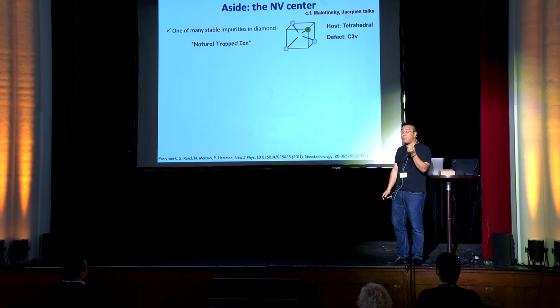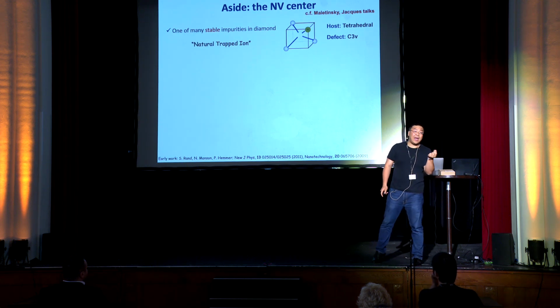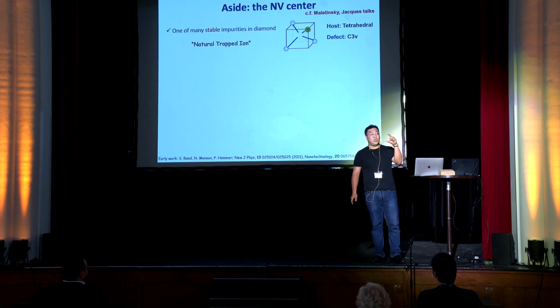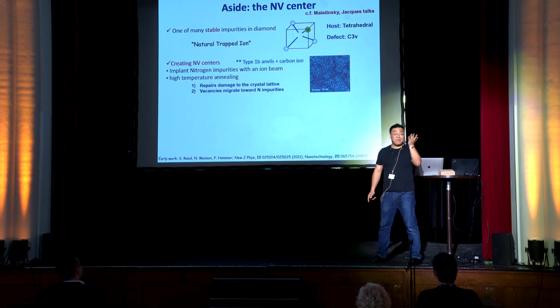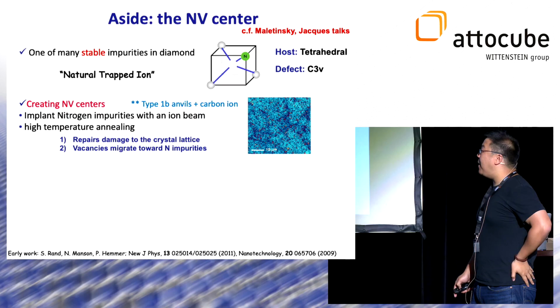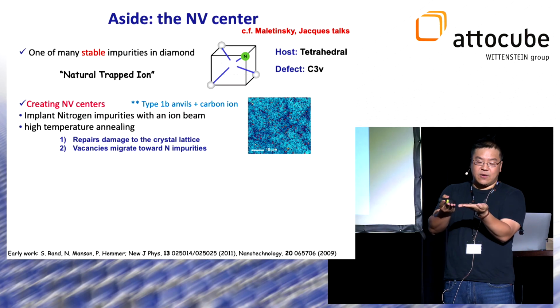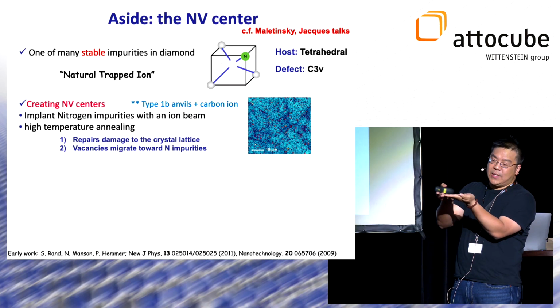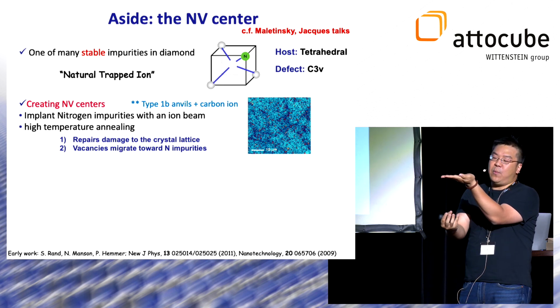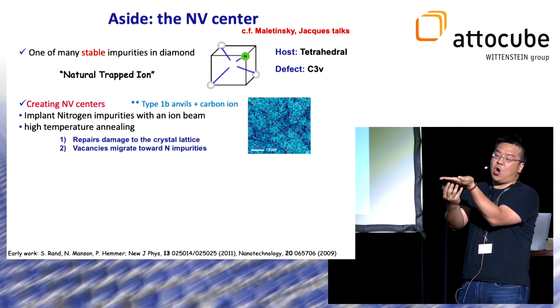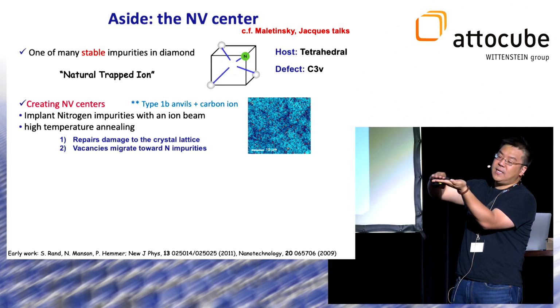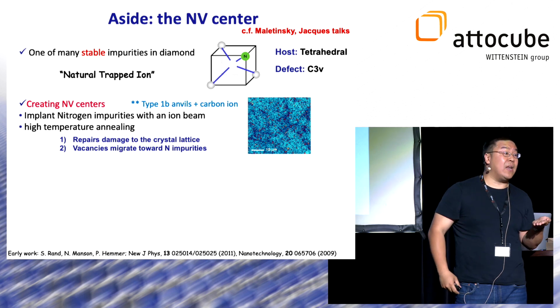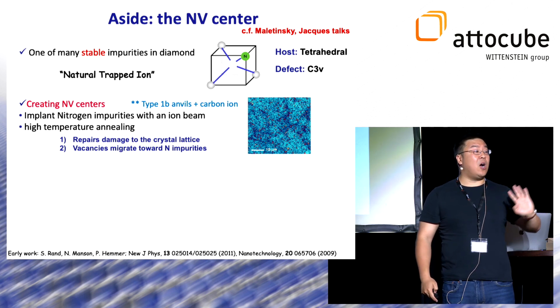NV centers are a particular type of defect inside diamond lattices, which correspond to a substitutional impurity of nitrogen adjacent to a vacant lattice site. And just in case there's someone who works on pressure, the way we make these NV centers inside the anvils is we take type 1b anvils and we do ion implantation of carbon to generate vacancies, and then we anneal to generate NV centers. So we're always looking at ensemble measurements.